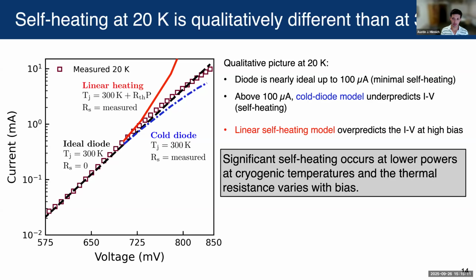And so that tells us that self-heating is clearly important, but there's some assumption in the current model for self-heating which is not right. And that assumption is that the thermal resistance is independent of bias. You can clearly see from the red line compared to the data that the thermal resistance has to depend on bias to explain the measurements.